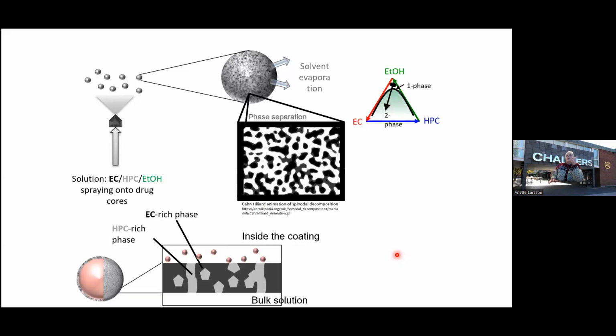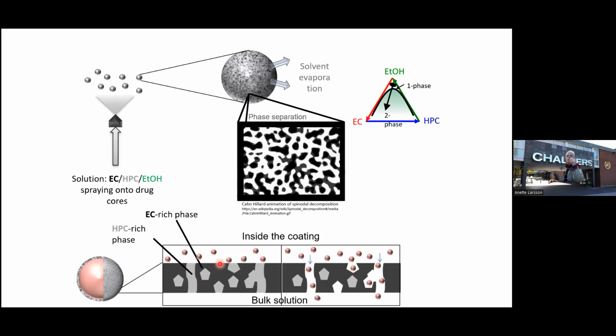And now, if we take that and have that here on the membrane, we have the API here. So we have this HPC phase here, and then we expose it to water. Then the water will dissolve the HPC, and then the drug can be released from inside the coating to the bulk solution. And here I want you to observe that we also have spots where the HPC regions are not connected. And these will not dissolve, and therefore will not create pores where the API can be transported through.